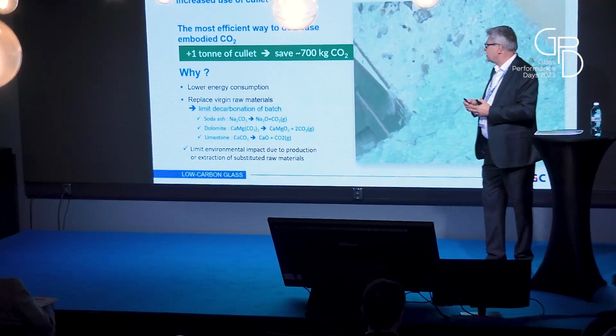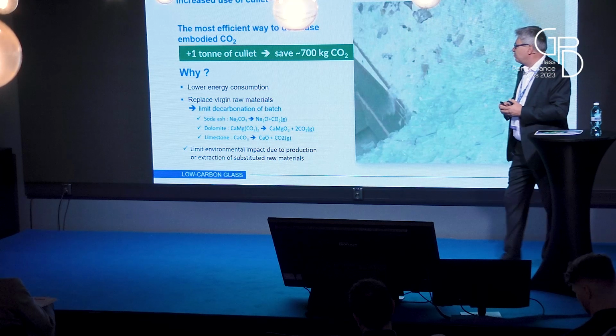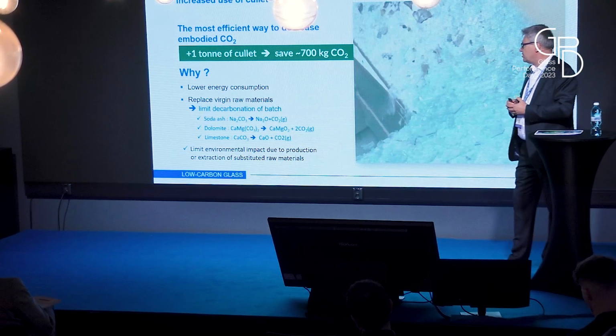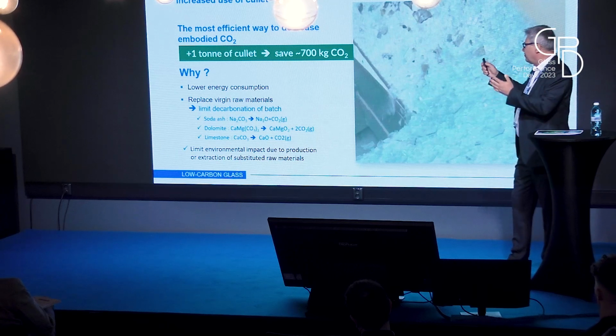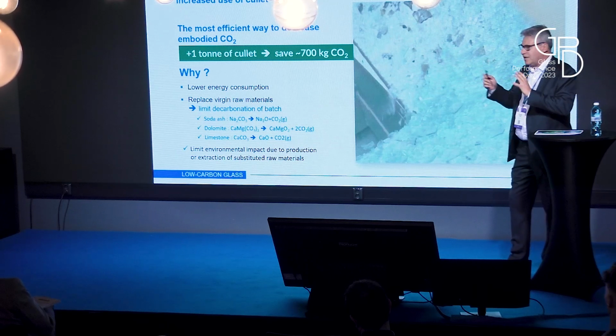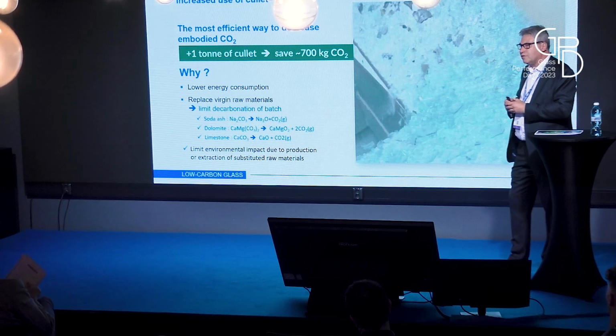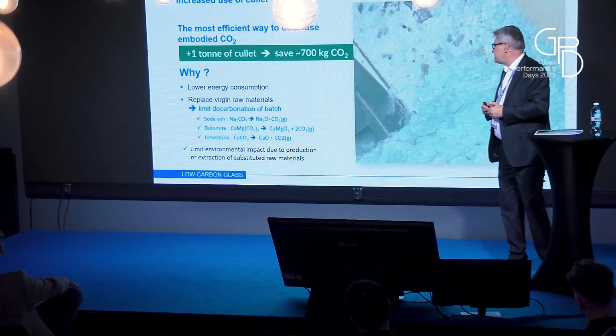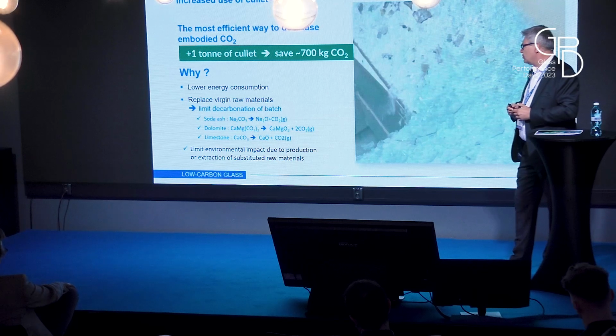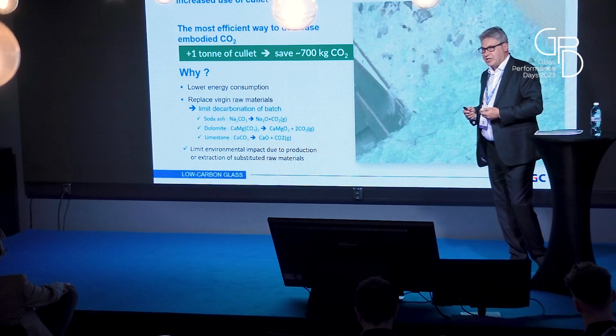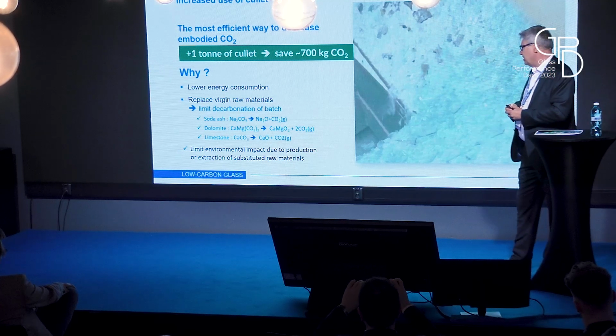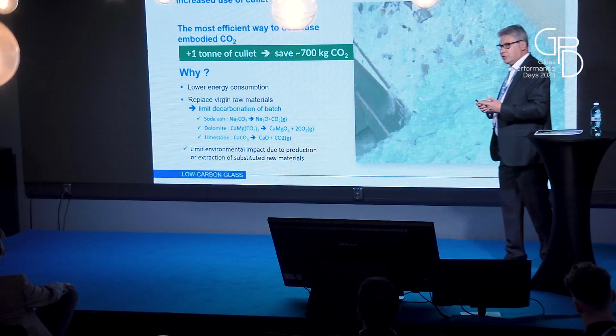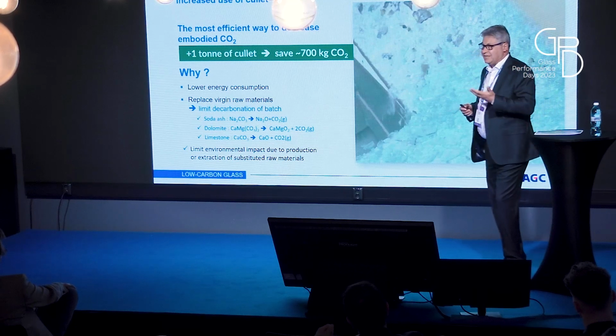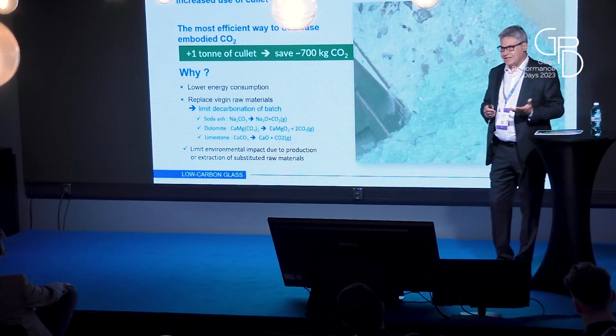So the third is the cullet. As I said, it is the most efficient way to decrease the embodied CO2. Different figures exist, but they are always in the same order of magnitude. For 1 ton of cullet more in the furnace, we save 700 kilos of CO2. Why? It lowers the energy to melt the raw material, but it also replaces virgin raw material by a material that is already decarbonated.